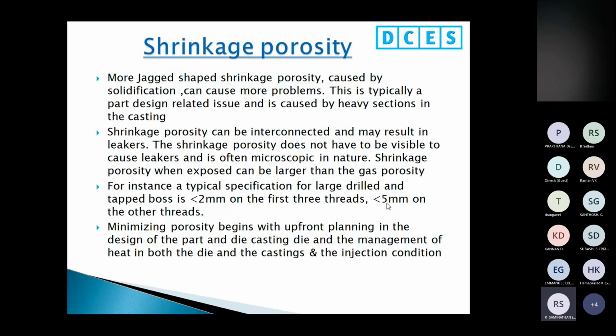Shrinkage porosity can be interconnected and may result in leakages. The shrinkage porosity does not have to be visible to cause leakage and is often microscopic in nature. Shrinkage porosity, when exposed, can be larger than the gas porosity. Normally, the shrinkage porosity will be larger than the gas porosity. For instance, a typical specification for a large drilled and tapped boss is less than 2 mm on the first 3 threads and less than 5 mm on the other threads. This is one type of specification.